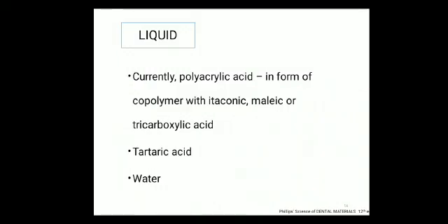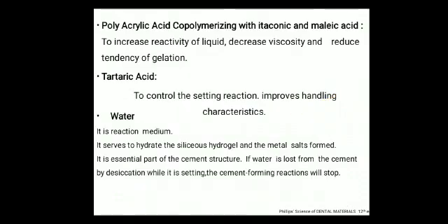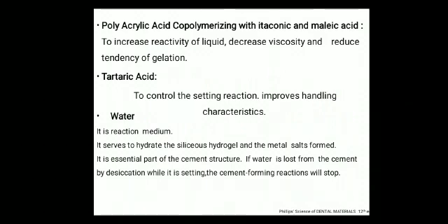Liquid. Liquid currently contains polyacrylic acid in the form of copolymer with itaconic, maleic, and tricarboxylic acid, tartaric acid, and water. Polyacrylic acid copolymerizing with itaconic and maleic acid acts to increase the reactivity of the liquid, decreases the viscosity and reduces the tendency to gelation.